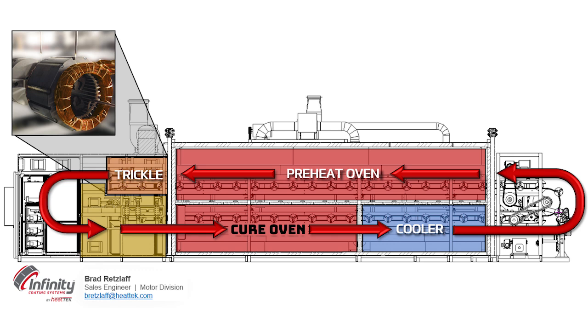Once in the bake zone, the E240 is rapidly cross-linking. Bake zone temperatures are typically lower with the ProPreg E240 at between 155°C to 175°C. This is an advantage over higher temperature curing polyesters by allowing customers to either increase index times in existing equipment or lowering temperatures in the bake zone. The E240, when compared to a polyester, can increase throughput and reduce energy consumption.